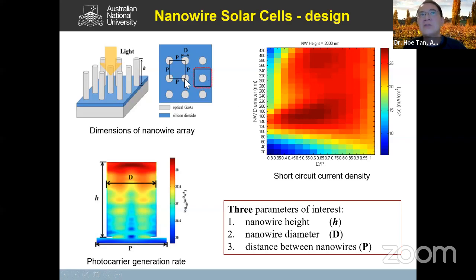The pitch is essentially the spacing between the nanowire. And as you can see here, this is the region we want to work with where you have the maximum short circuit current density. Again, in this region here, you can see the optimum nanowire diameter is about 180 nanometers and the diameter divided by the pitch is roughly about 0.6. And that's very easy to do, okay? We can just use our e-beam lithography and pattern this according to the dimensions that we want. And then the height of the nanowire is just strictly determined by the growth time.